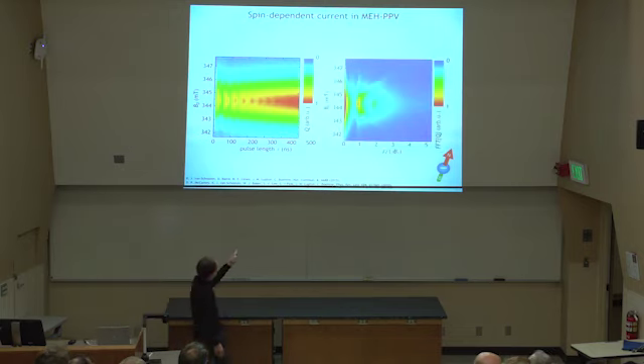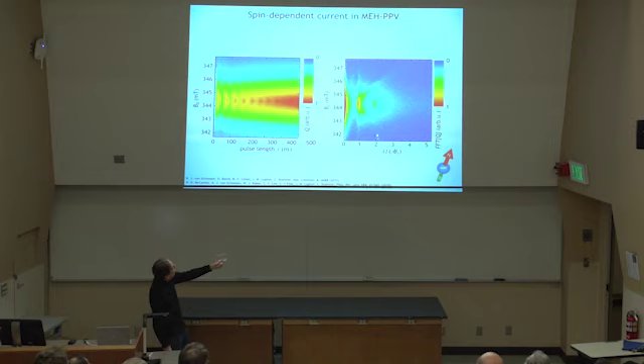So here you have a plot of frequency components, in units of gamma times B1. B1 is the amplitude of your driving field strength. And that means 1 corresponds to a spin 1/2. And you see here a pronounced imprint. You have these weird shapes. And then you have a straight line here. And then you have something at a spin of 2.